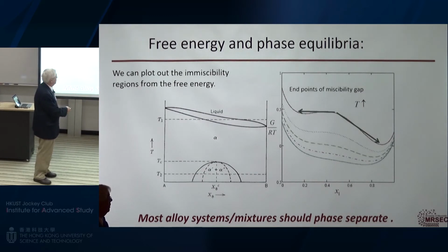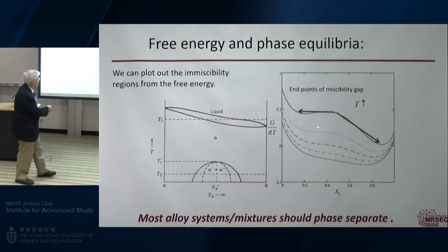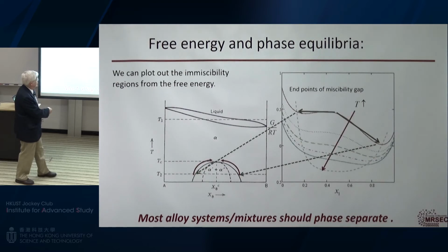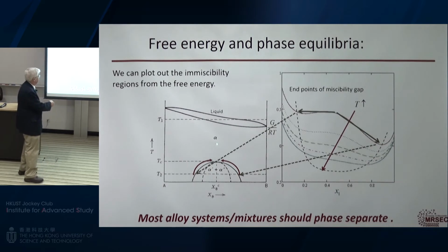It will eventually, if you calculate the free energy, it has these bumps in it, and that's due to the enthalpy of mixing, or the free energy of mixing. Those endpoints correspond to these points on the phase diagram. So if I cool it down at equilibrium, it'll generate some of this and some of this. And as the temperature goes up, it'll move up these curves until eventually I get to a homogeneous composition.